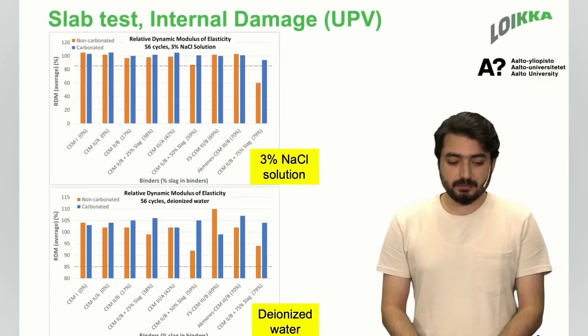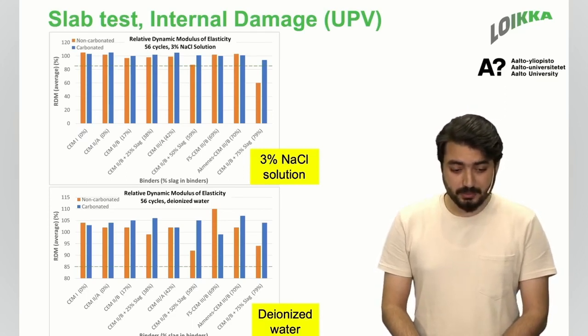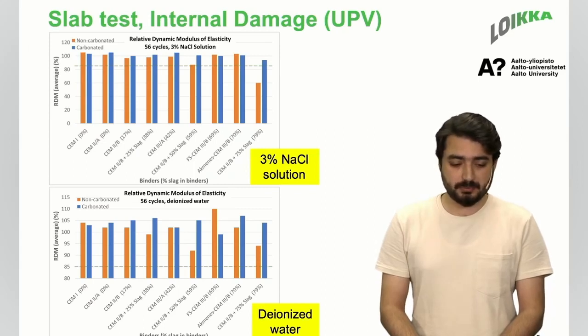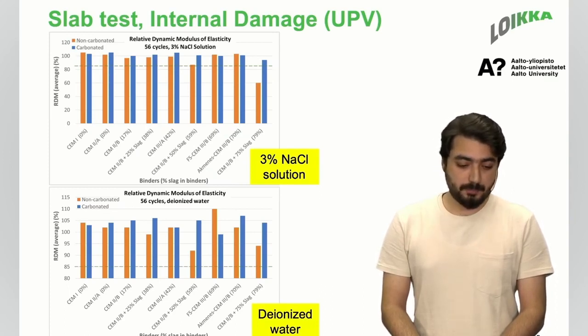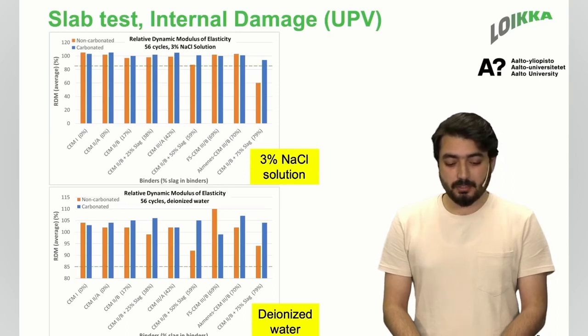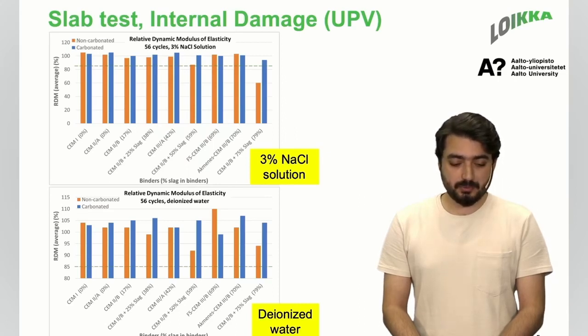Another parameter that I worked on was internal damage using UPV, also for salt water and deionized water. The dashed line is the strictest requirement, 85%, and you can see that all of the carbonated and non-carbonated samples passed that standard, except for the non-carbonated with 80% of slag. If we turn towards the deionized water, it passed this frost resistance standard with quite a margin. Here I would like to mention that for the case of deionized water, this UPV or internal damage was a better parameter to show the results than scaling.